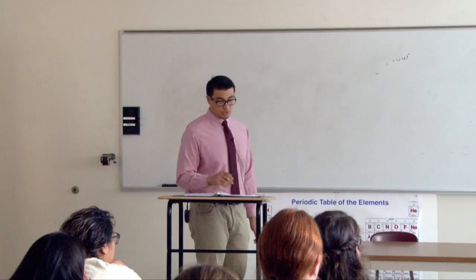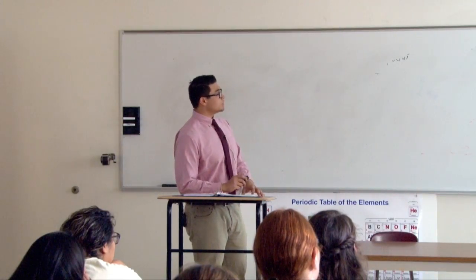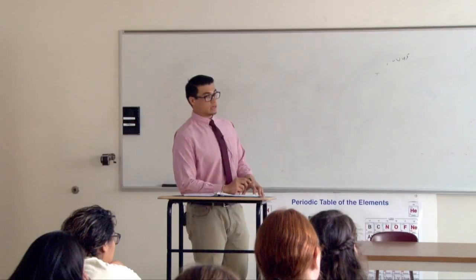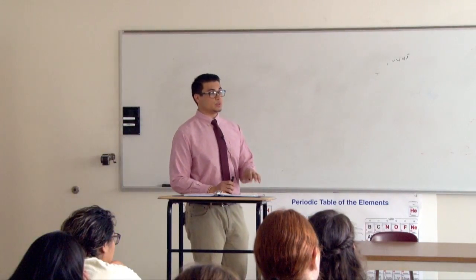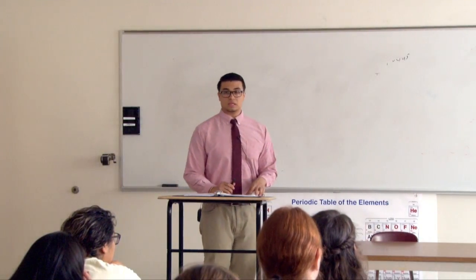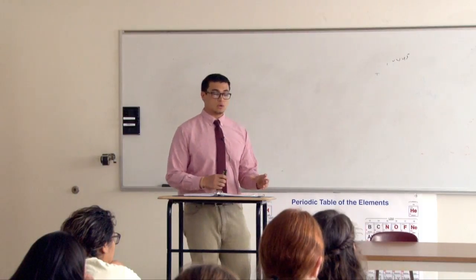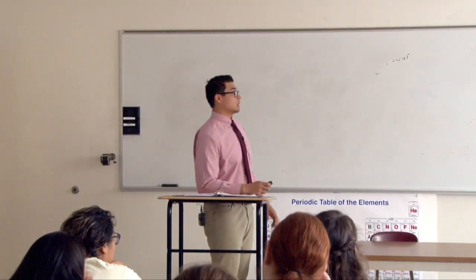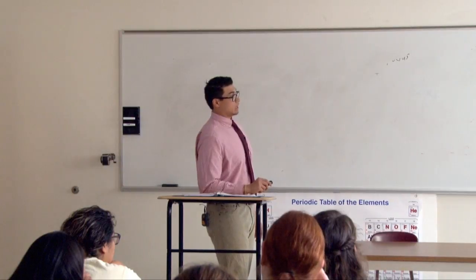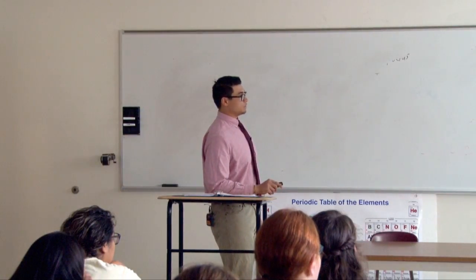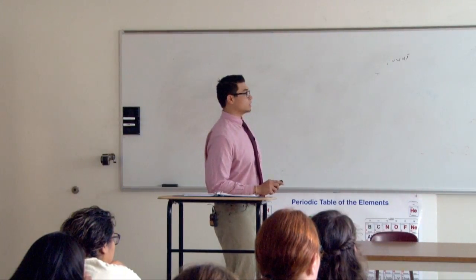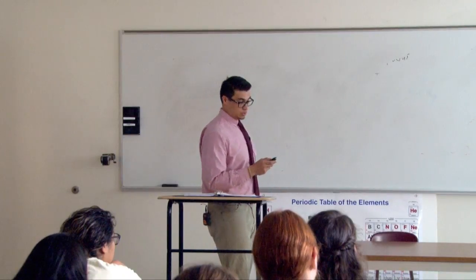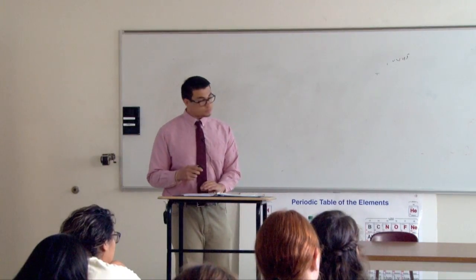So decomposition occurs for several reasons. The main ones we want to talk about is when the anion attacks the cation. We discussed how for ionic liquids we really want that anion to not interact well with the cation. We want to keep it as a large anion base and an asymmetrical cation. And also we want non-coordinating anions. So any reduction of the coordination ions, we don't want that at all. So to prevent decomposition, we want to keep that thermal stability high.